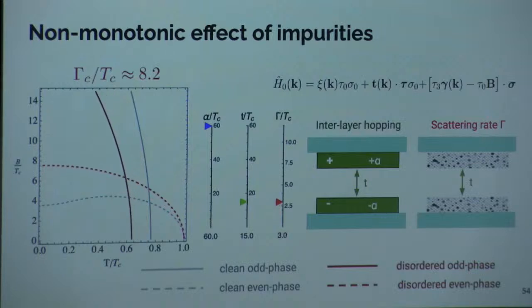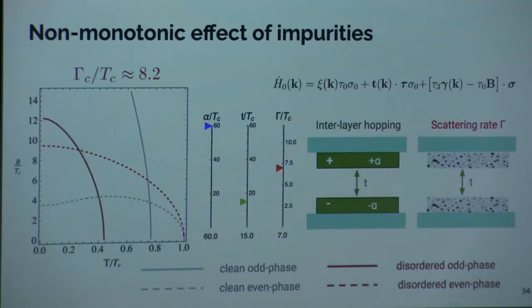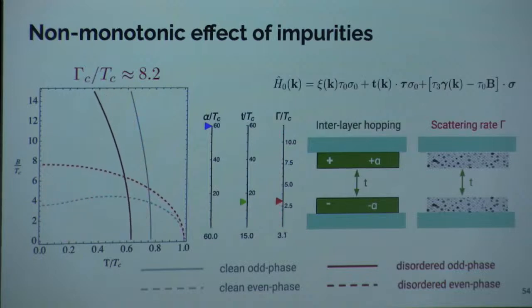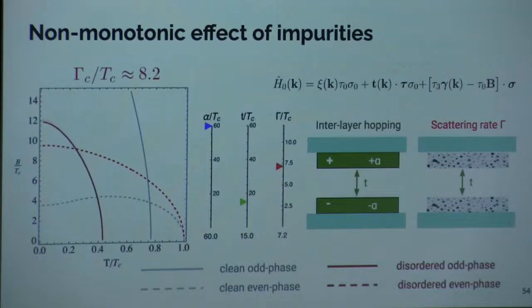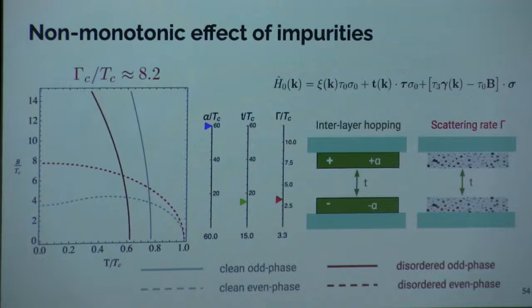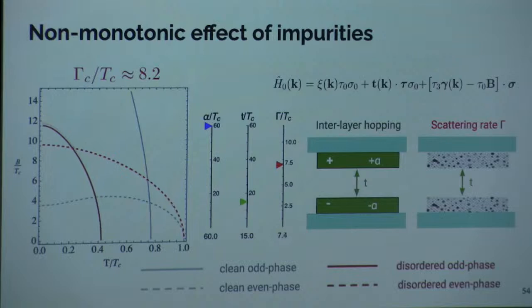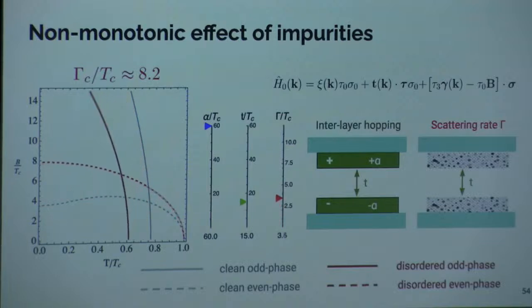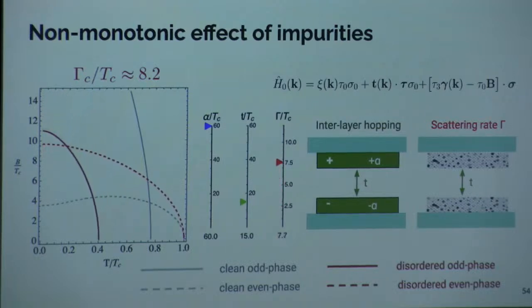Now we look at what happens if we add impurities. So this is done within the self-consistent Born approximation. I now added a third parameter that is changing, which is gamma. This is the scattering rate. Here I use somewhat more realistic parameters. Alpha and t go from 0 to 60, and gamma only varies from 0 to 10. Usually, for an unconventional superconducting odd parity state, these states are usually obliterated for a scattering rate of the order of 1. So here again, the red solid line is the disordered odd phase, and the red dashed line is the even phase.